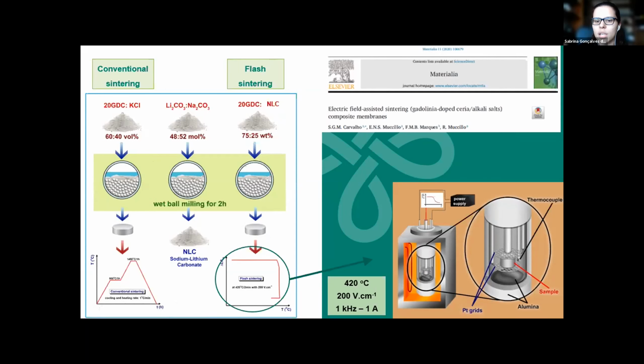And also the sample produced by flash sintering, where we prepare a mixture of Gadolinia-Doped Ceria with the eutectic mixture of carbonate. This mixture was cold pressed, and the sample was positioned between two platinum electrodes connected to a power supply, applying an electrical field of 200 volts per centimeter at a temperature of 420 degrees C to produce the dense membranes.